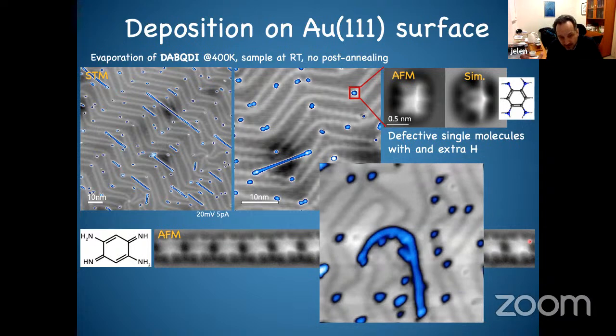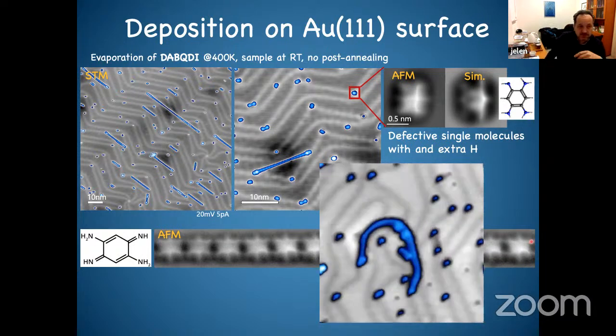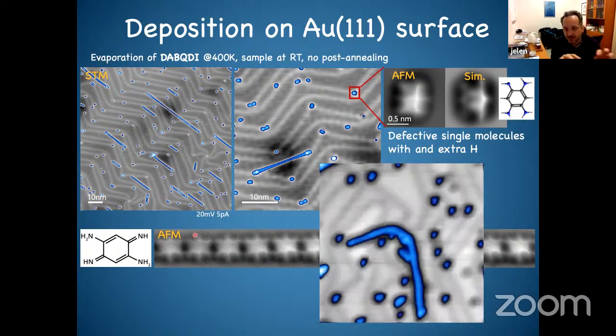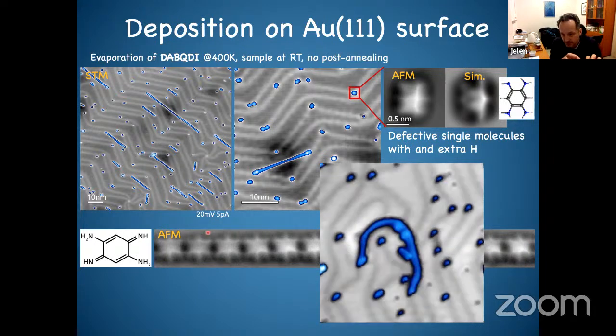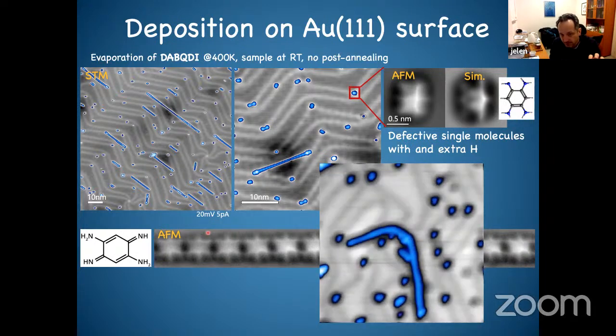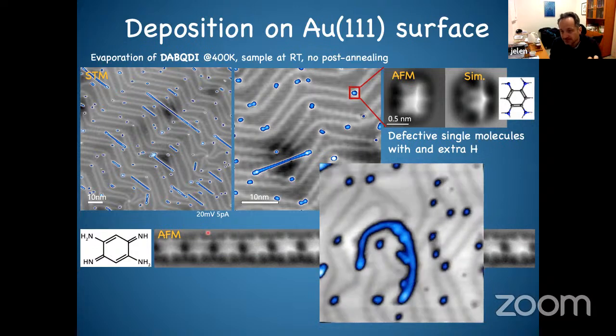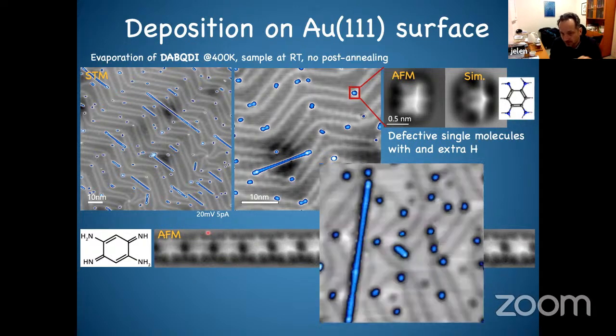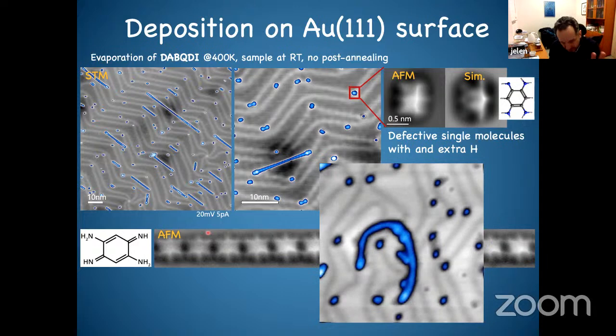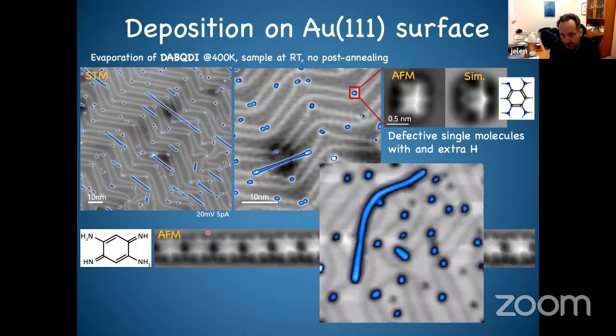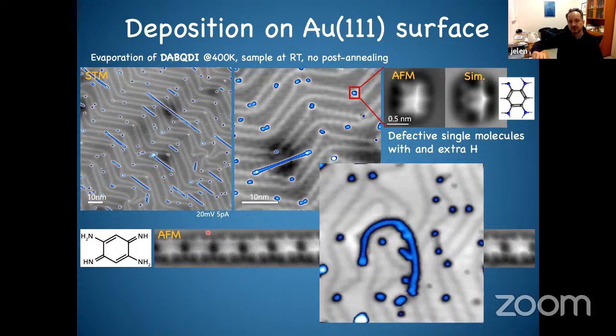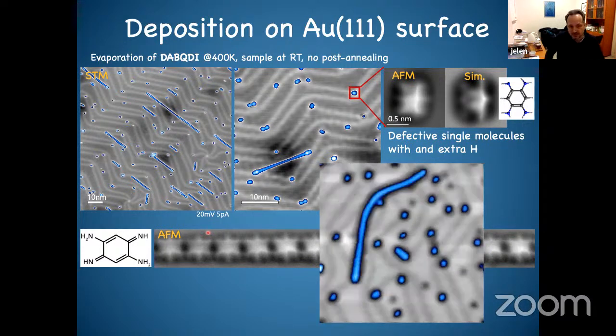That's something remarkable because in principle these molecules are connected by hydrogen bonds. But typically, when you have hydrogen bonds and you come with a tip, you will very easily disrupt the chains, or these supramolecular chains. But now, okay, I have to admit it's at 4 Kelvin, but now we can come with a tip and move it, and the chain is very stable.